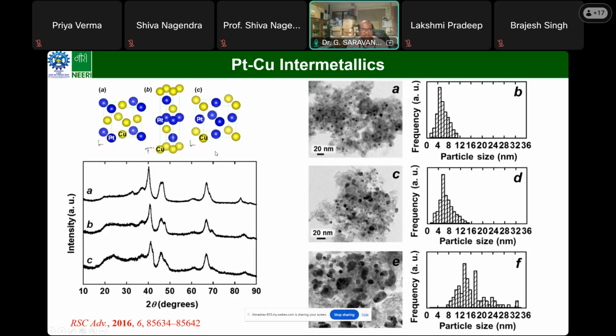And as usual, we performed post-mortem analysis after catalytic reactions, and we found these two, Pt3Cu and PtCu combinations, showing the same phase, whereas the PtCu3 is not stable. So that means it is not recommended for these applications. You can go with one of these two. But when we see the morphology after the reaction, the particle size is almost closer to the initial size, roughly 3 to 4 nanometers.